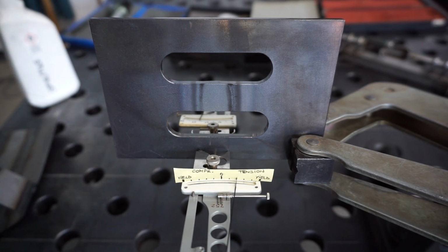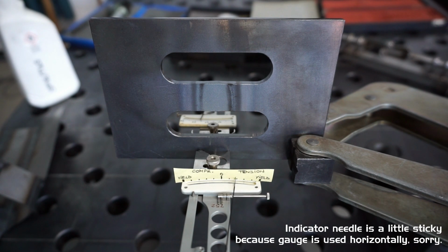Explained in other words, the heated spot is now thermally expanded. It can expand in width and thickness direction of the bar quite freely. That means free of stresses. But the expansion in length direction here is something the outer bars don't like. They constrain it by compressing the central bar. The outer bars, in turn, get pulled apart by the central rod's expansion in length direction. This behavior has a certain balance, which is controlled by the bars' cross-sections. But now, let's watch what happens during cooling, and for this I'll speed up the video.